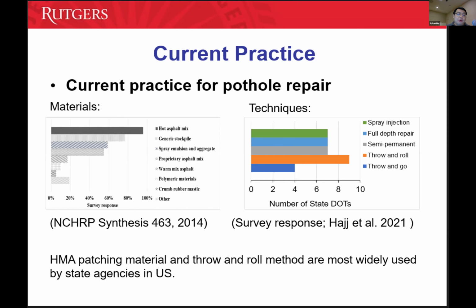Throw-and-roll is the most common one. In this case, you do some quick compaction, sometimes using truck tires, just driving a pickup or other small truck over the patch, or using a plate compactor to do very quick compaction. The semi-permanent one is more like you clean the pothole, you make it a rectangular shape, and then you do the repair. So you do more work and try to make the repair last longer. Based on this, we have focused on the boundary between the semi-permanent and the throw-and-roll, because this is considered a quick repair and also has potential for longevity.